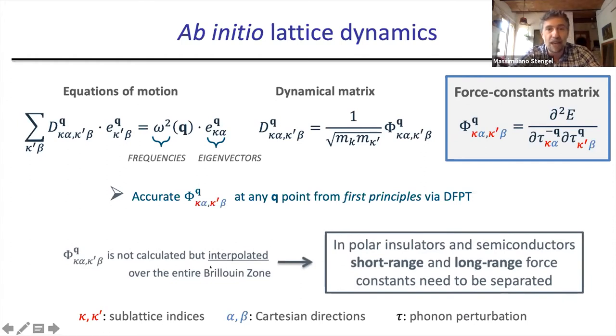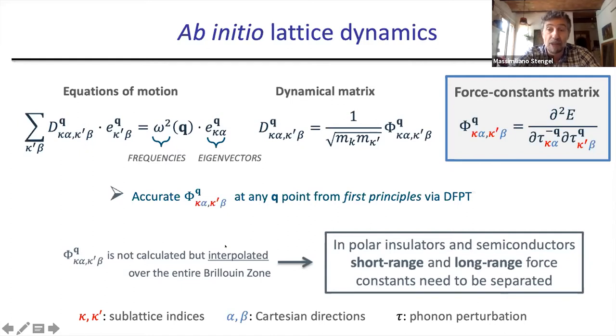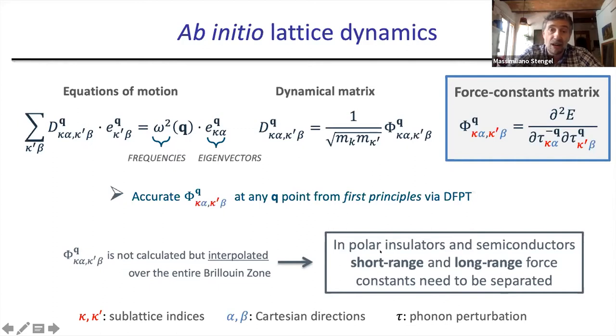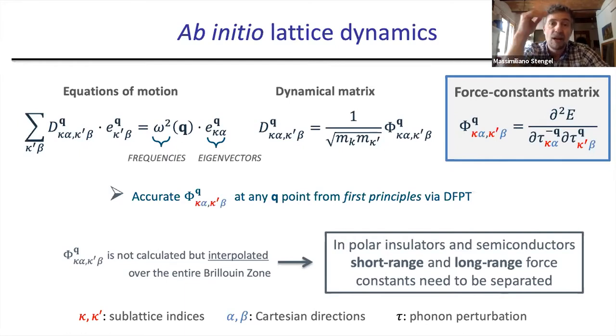In practice, for most applications, phonons are not calculated directly over the whole Brillouin zone, but are rather interpolated — with explicit calculations only on a coarse grid, on a coarse k-mesh in reciprocal space. It is therefore essential in polar insulators to be able to separate short-range and long-range force constants in order to perform such an interpolation.